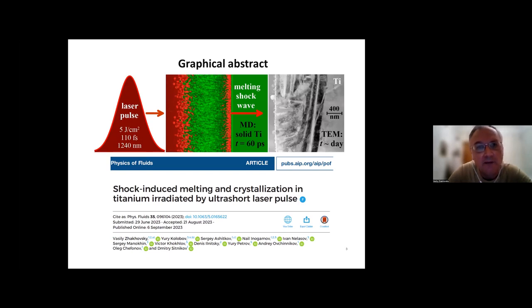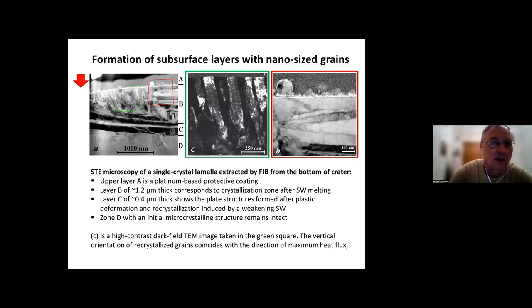On the same day, or maybe after one day, the sample irradiated by this laser pulse was analyzed using electron microscopy, transmission electron microscopy of the subsurface layer. And you see on the right side here that indeed the surface of the material is modified significantly. So what we found in our experiment is the formation of two modified subsurface layers.